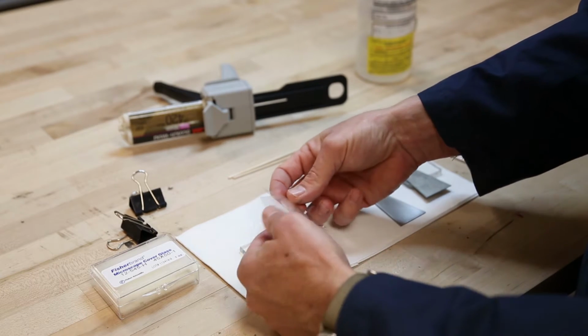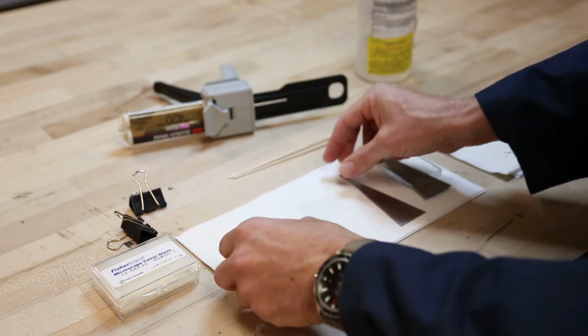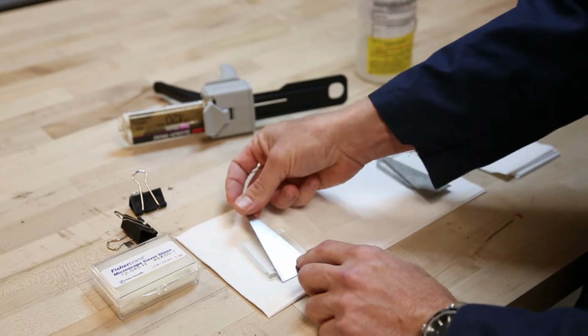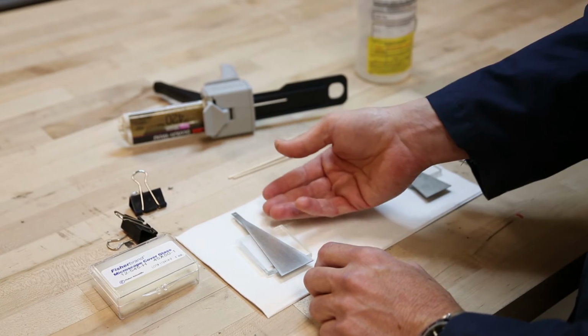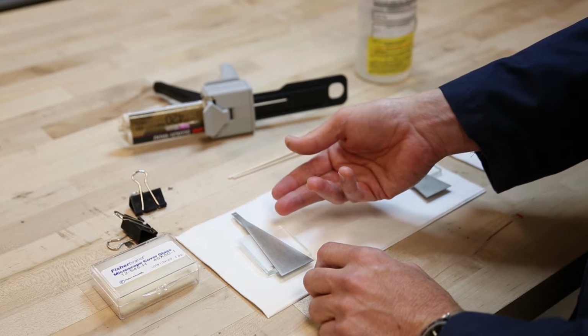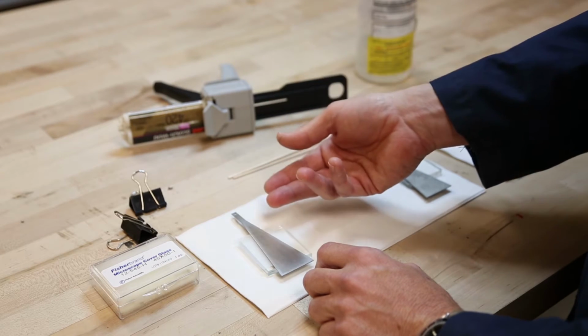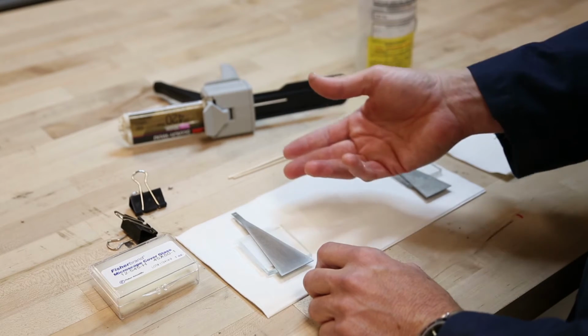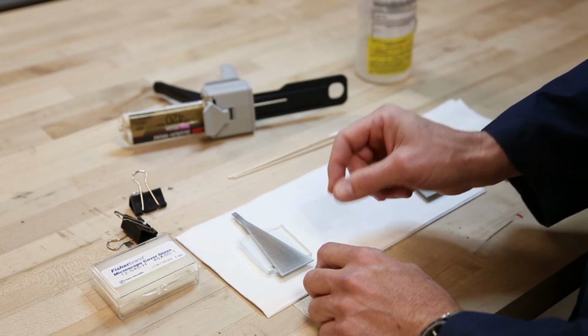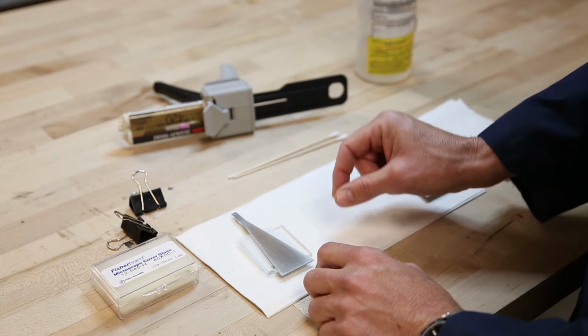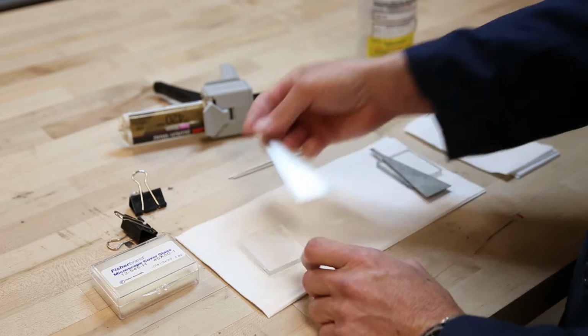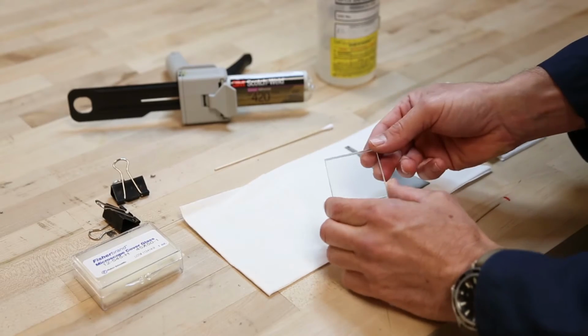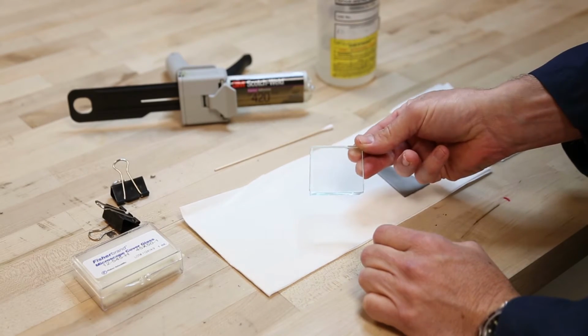For instance, if I were just to laminate my titanium beam to my large slide of glass, if I do my test, I might open up the interface between the encapsulant and the titanium, and that's not what I'm interested in testing. I'm interested in testing the adhesion between the encapsulant and the glass. So after I do the lamination, this is what it looks like.